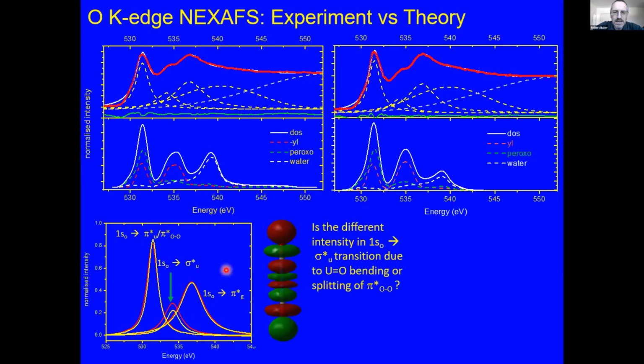So this one, really, everybody knows what a sigma star U orbital looks like in a uranium complex, right? So this is the Kohn-Sham canonical orbitals for a uranyl ion, okay? And you can imagine that if this bends, then you could see a change in the intensity of these transitions. Or it could be the fact that the peroxy groups are actually getting involved in the bonding. And so how can you tell the difference between these two?